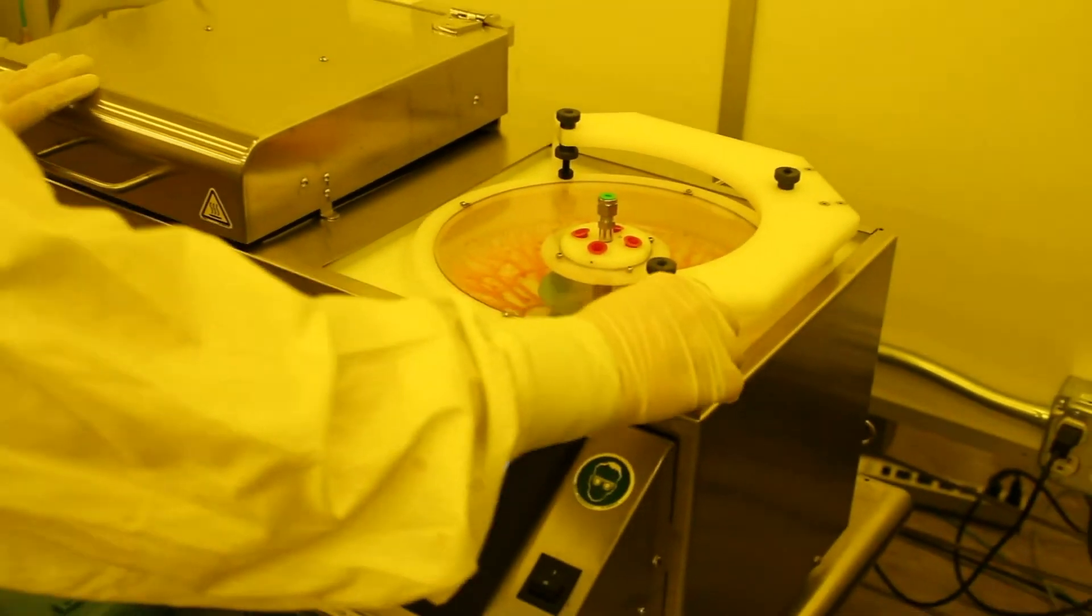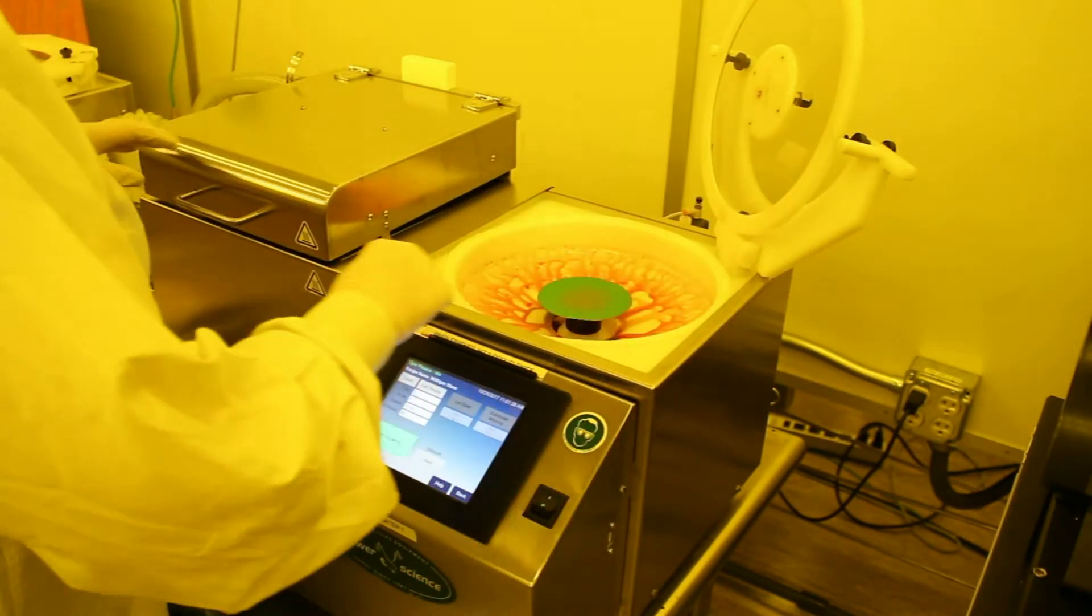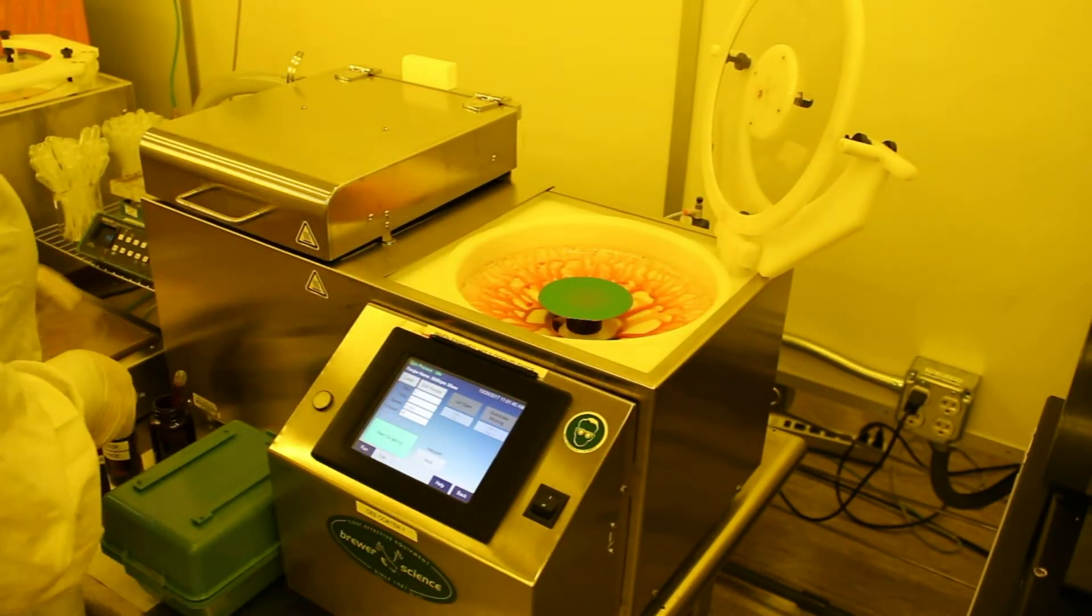Once the spin process is done, the wafer is removed and put on the hot plate to bake at 100 degrees for 60 seconds.